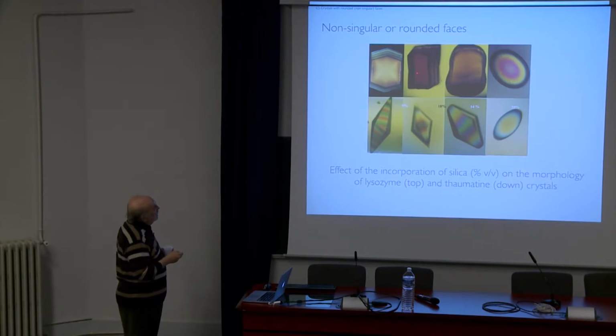crystal shape, flat faces. If you grow this crystal in increasing concentration of a silica solution, okay, you can see that you start to lose the influence of the internal structure, I mean the anisotropic internal structure, and you can finally have a rounded crystal, okay? Or here, this is thaumatin, another protein, in which you can see that you lost the influence of the internal anisotropy, and finally you have a crystal which is completely rounded.